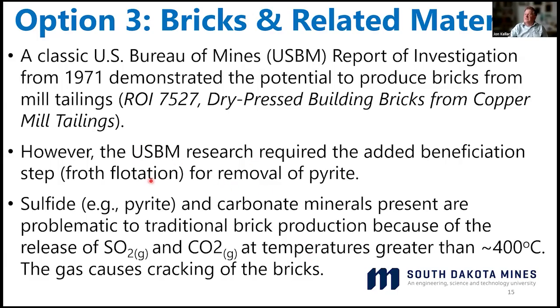One of the drawbacks of that research, though, showed that you had to actually remove the pyrite from the tailings. Pyrite's a bad actor when making bricks because we're going to have to fire the material, and if you fire it above about 400 Celsius, SO2 comes off. So I think that was probably the biggest drawback to that research, that you had to reprocess the tailings to get rid of the sulfides. And since you're producing a low value product, that extra processing step doesn't make a lot of sense.